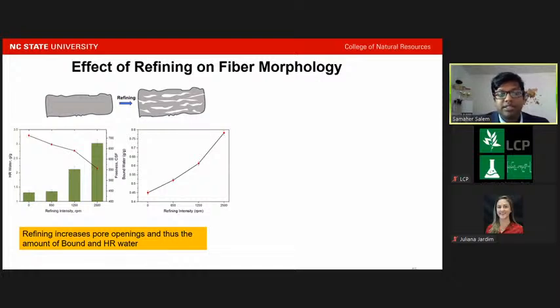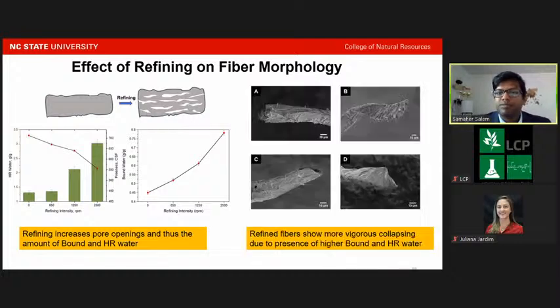Thus, it can accommodate more and more water into the newer substrate sites and form hydrogen bonds with the newly exposed cellulose hydroxyls, which increases the bound and hard to remove water content of the pulp. And the SEM image shows that the refined fibers suffer more collapsing than the unrefined fiber due to its higher hard to remove water content and holding capacity.